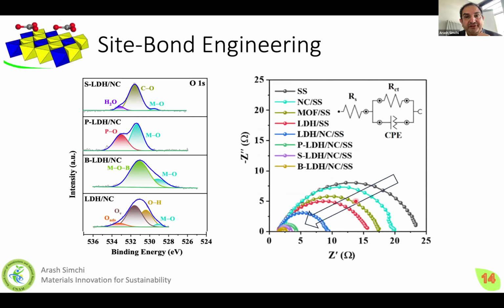We test this hypothesis as you see here. Don't care about the numbers, for example, phosphorus, sulfur, boron, and so on. I just want to show you this is the EIS, electrochemical impedance spectroscopy, and these are the Nyquist plots. You see that the conductivity increases significantly. If this is true, then we have to see the fingerprint on the electrolyzers very well.